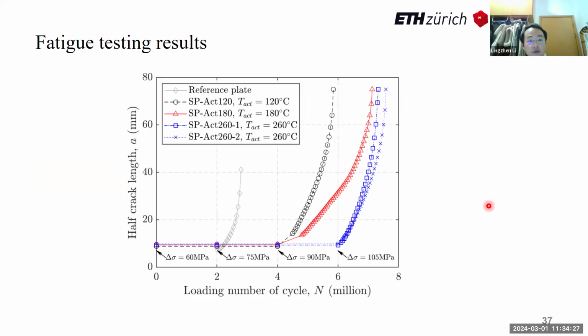This figure shows the fatigue testing results of 5 samples. Here, this gray one is a reference steel plate with a central through-thickness crack, but not strengthened. It had fatigue crack propagation at the load level of 75 megapascal delta sigma. After strengthening, all specimens survived at this load level. A minimum load level of 90 megapascal was required to drive the existing fatigue crack to propagate. And through the test, we found that a higher activation temperature has better strengthening efficiency.